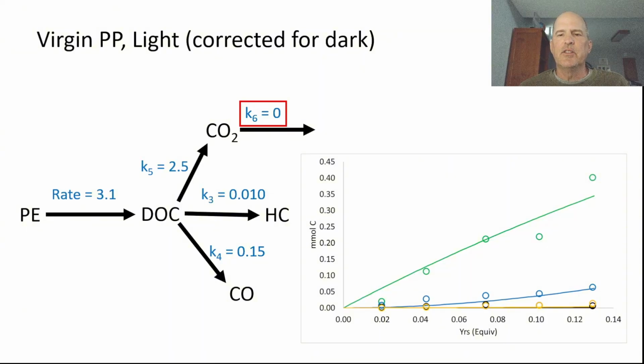I think it's because if you back out the total amount of CO2 that's generated from the ocean polypropylene one compared to this one, it's a lot more. It's like 10 times as much. I suspect it might have something to do with overcoming the natural buffer that's in seawater. Seawater has some boric acid and some sodium bicarbonate in it, so there's a little bit of a buffer in there. And I'm thinking maybe the CO2 only starts to escape once it's generated enough acidity in the water to overcome that buffer. And then you start to get this partitioning out of the water into the stopper. That's the best guess I've got. It could be something else.